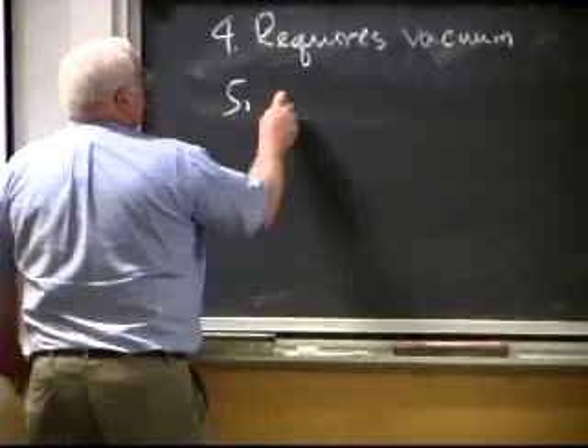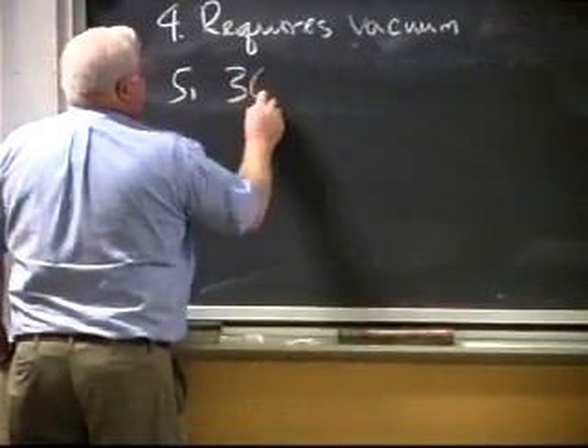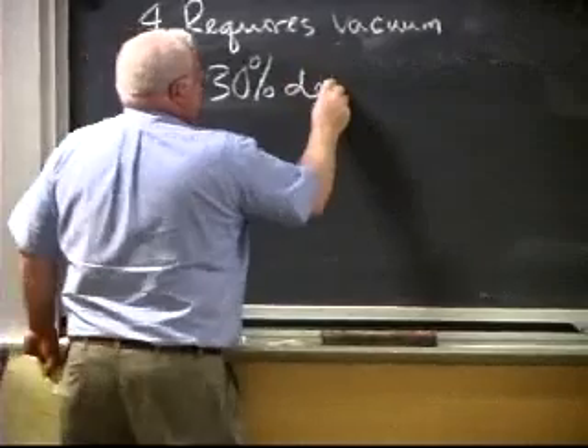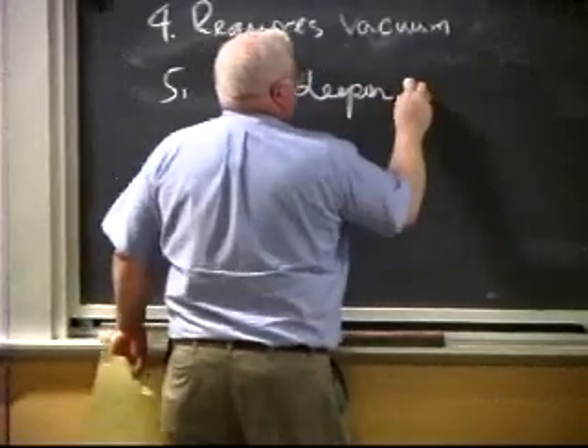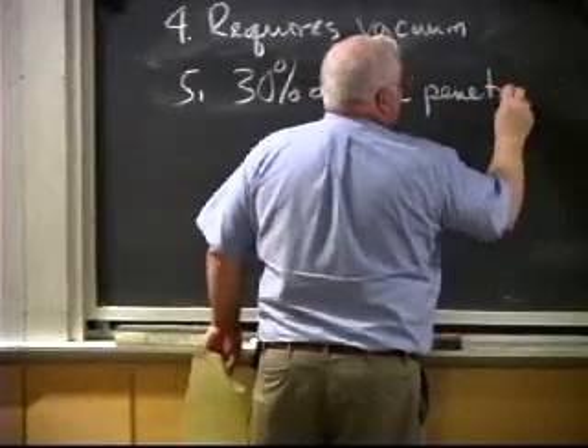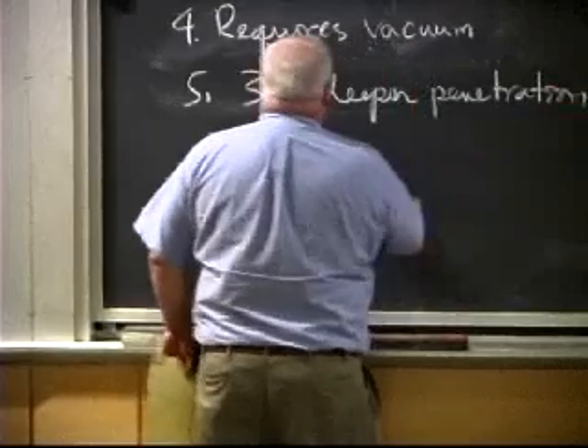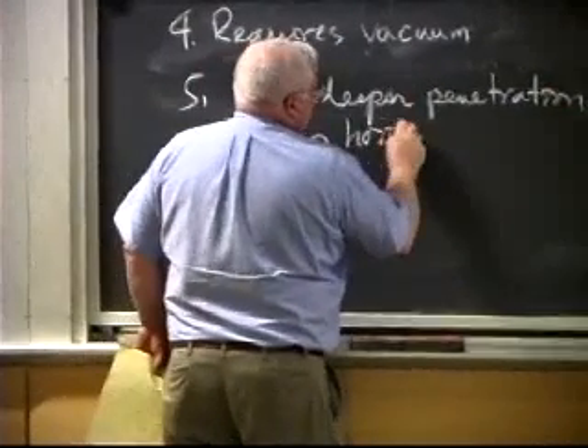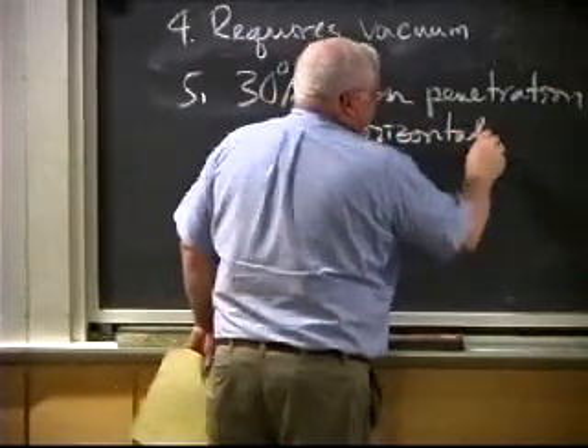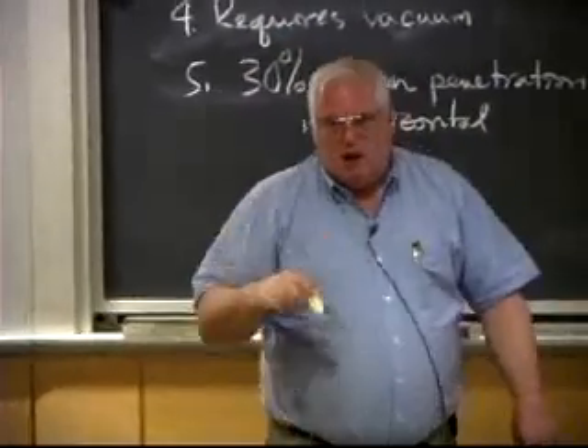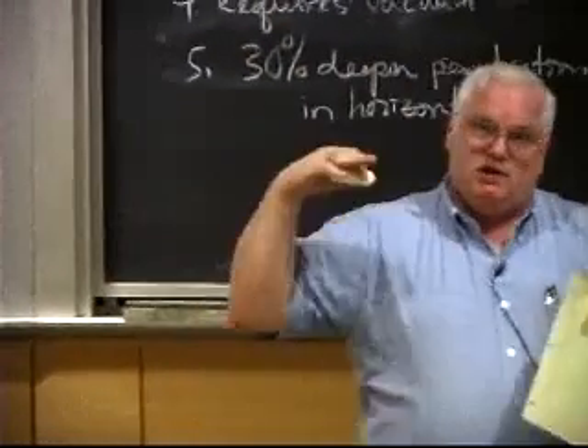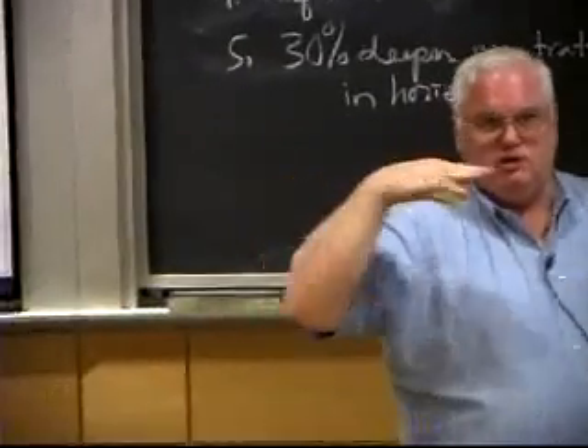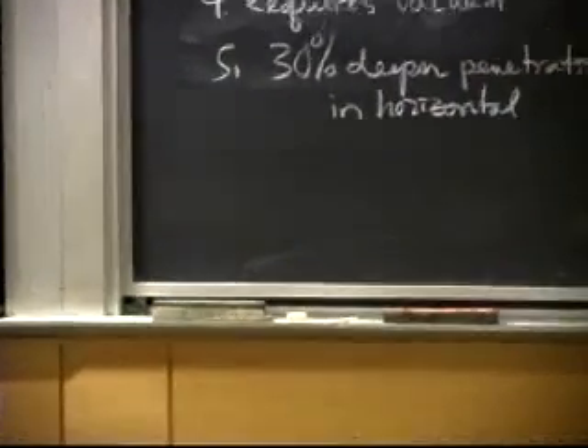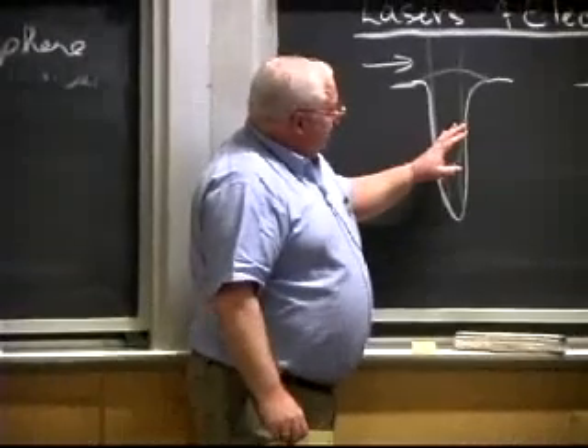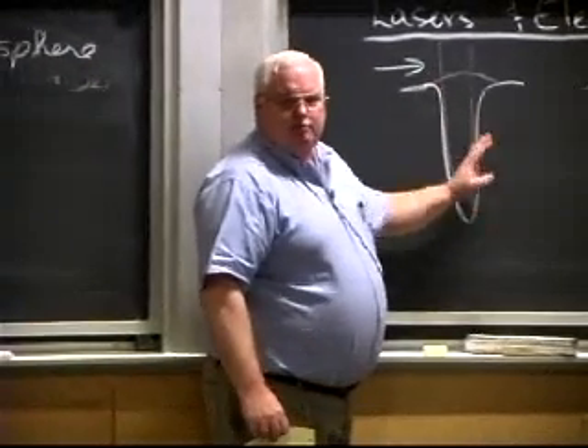Another thing is you get 30% deeper penetration in a horizontal position. So if I'm welding from the top straight down, I will get one penetration, and if I turn everything 90 degrees and I make a weld from the side, I will get about 30% greater depth for the same beam parameters.